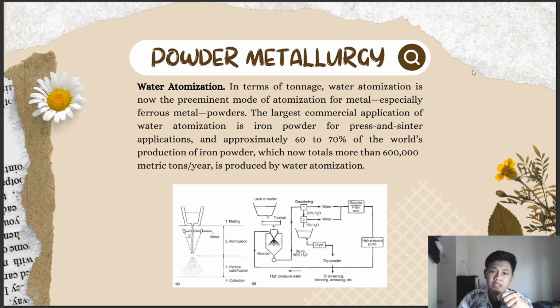Water atomization. In terms of tonnage, water atomization is now the preeminent mode of atomization for metal, especially ferrous metal powder. The largest commercial application of water atomization is iron powder for press and sinter application, and approximately 60 to 70% of the world's production of iron powder, which now totals more than 600,000 metric tons per year, is produced by water atomization. So this is the process of water atomization in powder metallurgy. This is melting, atomization, particle solidification, and collection.